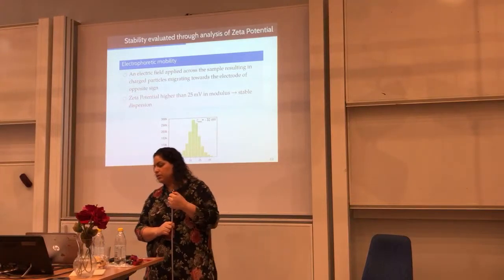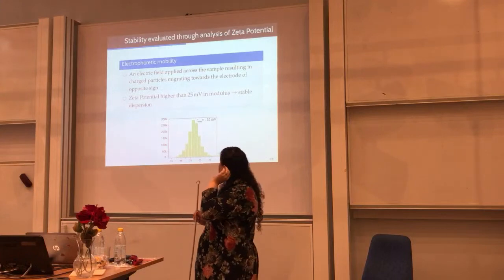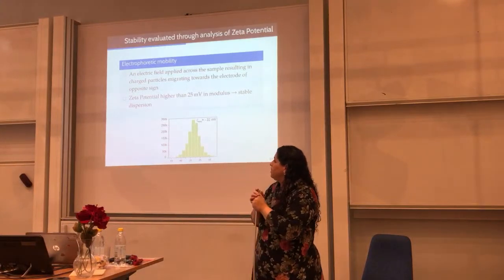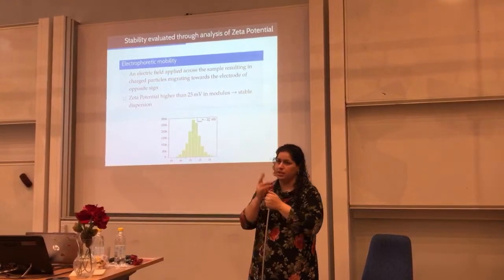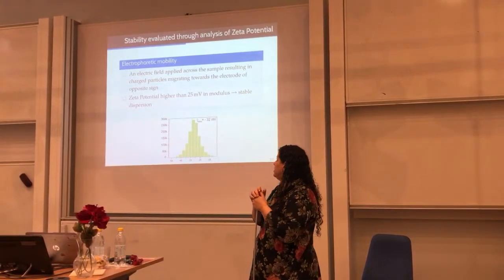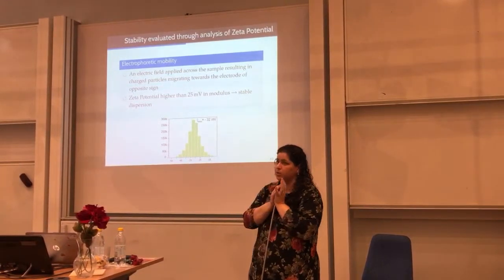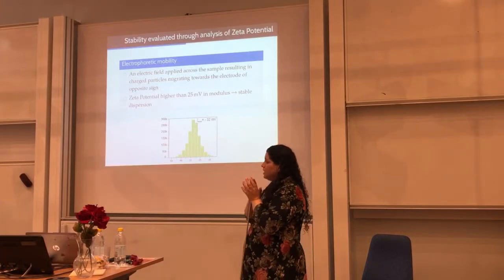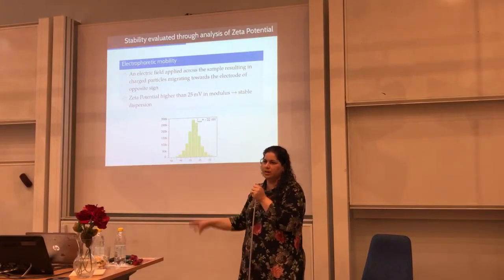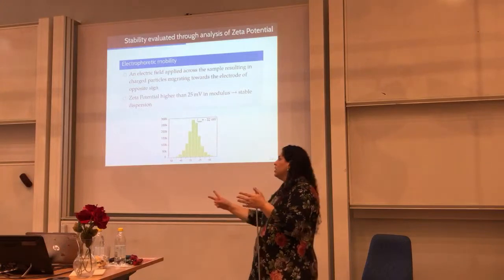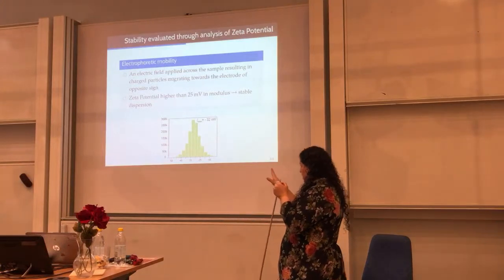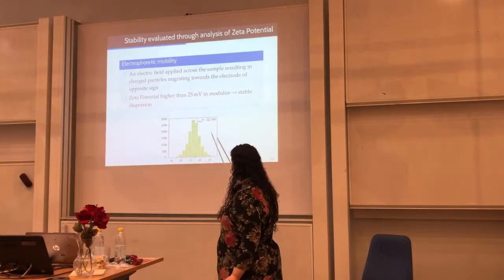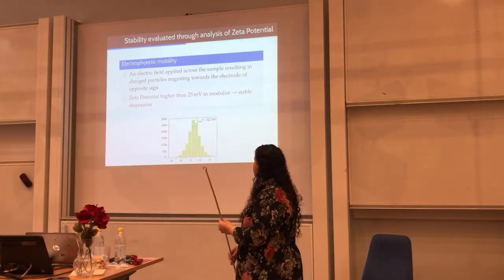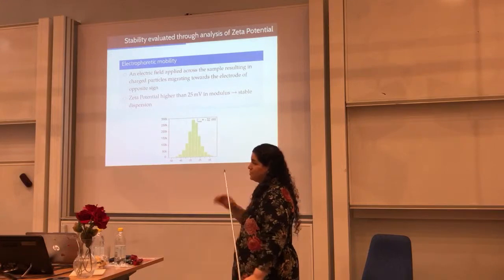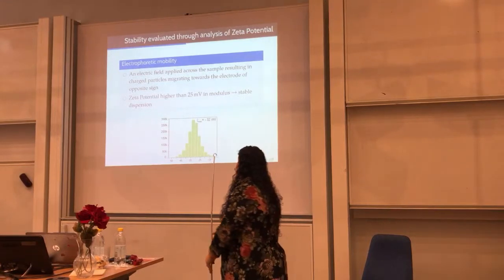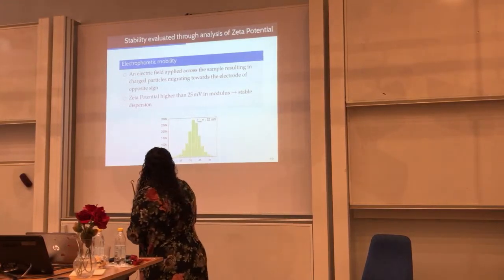So how do we measure the stability? In my work, I measure stability in two ways. First, I measure the stability through electrophoretic mobility, using the same instrument that I can use to measure the particle size at the same time. So it's great. It's two shots at once. You measure the electrophoretic mobility with this device, and from it the zeta potential, because measuring zeta potential directly is really not possible. You always have an estimation of it.